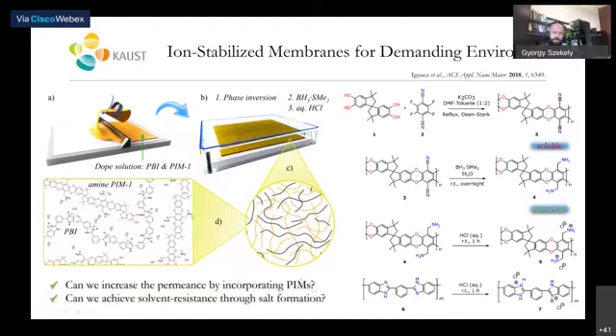Okay, so PIM stands for polymers of intrinsic microporosity. Here you can see examples of these structures. And these materials, for instance PIM-1, it's a linear polymer that has an extremely high surface area. It's about 700, 750 square meters per gram. So it's assumed that if we incorporate these polymers into the membrane, then we're going to have a high throughput.